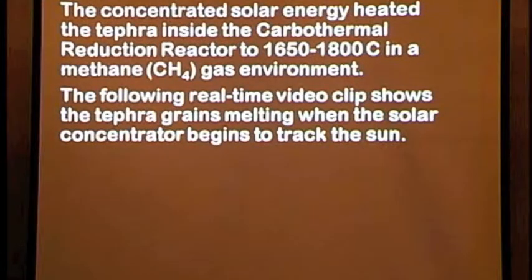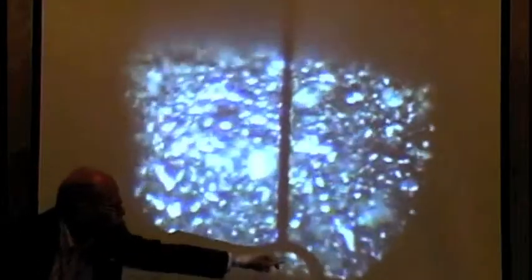Did you say that that module produces enough heat to melt that regolith? Well, in that one spot, yes. Absolutely. Here's how it does it. This is what it looks like. Now, this is 2 millimeters across down here in that reticle. So this is all blown up, but you can see as soon as you turn on that sunlight, it delivers it to this area, and the material starts melting and agglomerating and moving around.